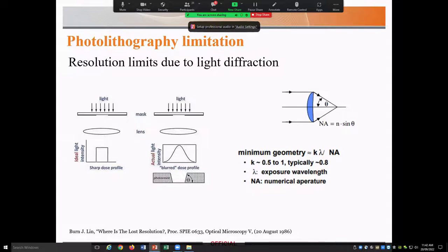So from what we said so far, we can tell that photolithography, optical lithography, is a very common technique that is used to print large area integrated devices. But it's got some limitations. Basically, the resolution of the conventional photolithography technique is negatively affected by light diffraction. And this makes it difficult to use this technique when we are printing ultra-high-density integrated devices.